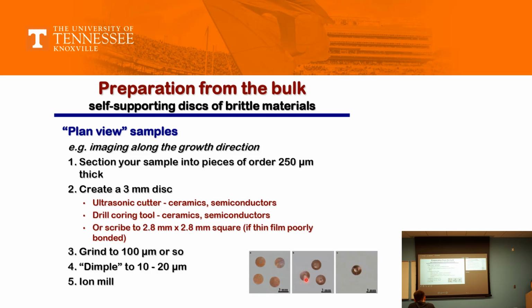You dimple it mechanically, and then either by electropolishing or by ion mill, you try to create a small hole inside. Then you look at the edges of the hole and analyze your sample. Anyone involved with iron samples would be doing this. Now with ceramics, it won't work. Why? Every kind of material has a particular technique. I did my PhD on titanium carbide and silicon carbide ceramics. Why do you think this kind of technique is good for metals?